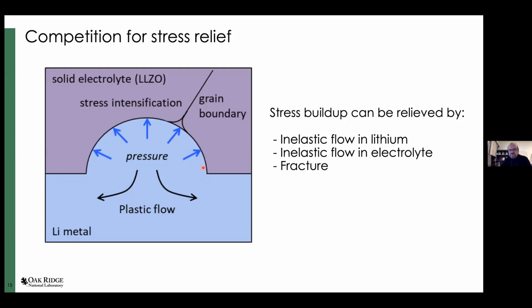You cannot build up elastic strain until very high values, right? It needs to be released somehow. It can be reduced by inelastic flow in lithium itself, by triggering some kind of dislocation motion in lithium metal, or creep, depending on the time scale. It can be relieved by inelastic flow in the electrolyte itself. And the third mechanism, which unfortunately we encounter in the majority of cases, is fracture that will reduce the stress buildup. So our goal here is somehow to trigger these two mechanisms in either lithium or electrolyte to avoid the third way to reduce the stress.